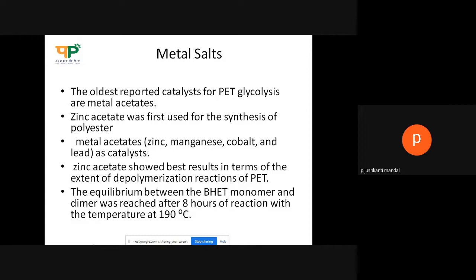by using the depolymerization process, using zinc acetate as a catalyst, and temperature and time are very important. At 190 degrees centigrade temperature and an 8-hour reaction, more than 95% yield of the polymer to monomer is obtained by using this catalyst. So the role of the catalyst is very, very important for the glycolysis process. So zinc acetate plays a very important role for the synthesis of the polymer to monomer. Metal acetate, zinc acetate showed the best result for the depolymerization, and this depolymerization reaction carried out at a temperature of 190 degrees centigrade for 8 hours will give the best result, meaning conversion of the polymer to monomer. Yield percentage is very, very high using the zinc acetate as a catalyst.